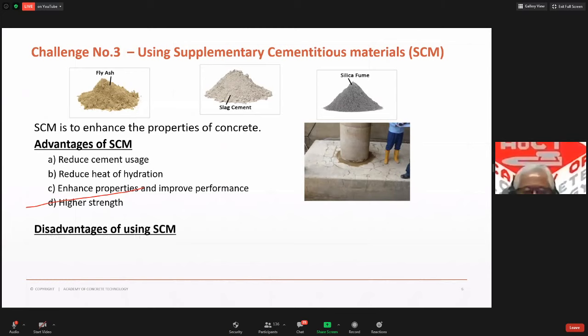A little bit about the disadvantages of using SCM, sharing my experience. Of course, first, it delays the concrete setting. Normally, if you use ordinary Portland cement, it would take probably 3 to 5 hours for the concrete to achieve initial set. What I mean by initial set is that you can actually walk on the concrete, your foot wouldn't sink in. That's where you can go in and start your work, your power float process and all that. But if you use, let's say, 30% fly ash in the concrete mix, you can't go in within 5 hours. It would delay the setting probably 8 to 12 hours. So it's not very good for people like us, waiting for the concrete to set. So that's one thing.